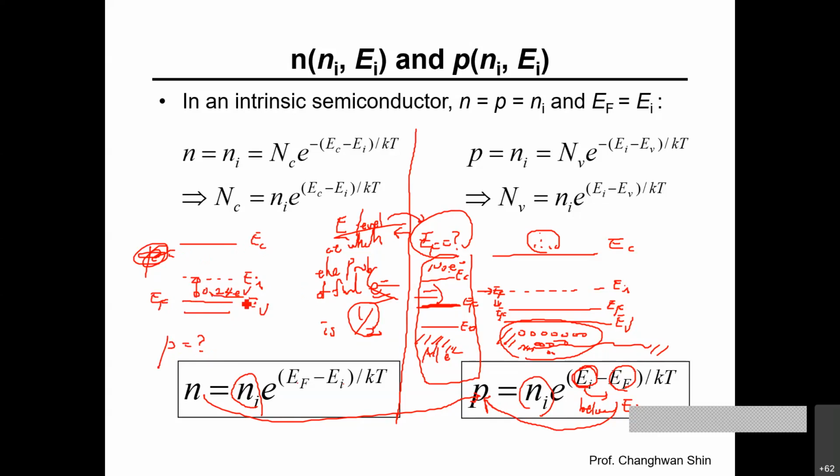That's easy: 0.24, okay, 0.06 electron volt times what? 4. Then this EF is close to the EV, so it is p-type. The majority carrier is hole, so the majority carrier concentration, or hole concentration, is 10 to the 1, what? 4. Plug in here. So the answer is the hole concentration is 10 to the 14 per cubic centimeter.